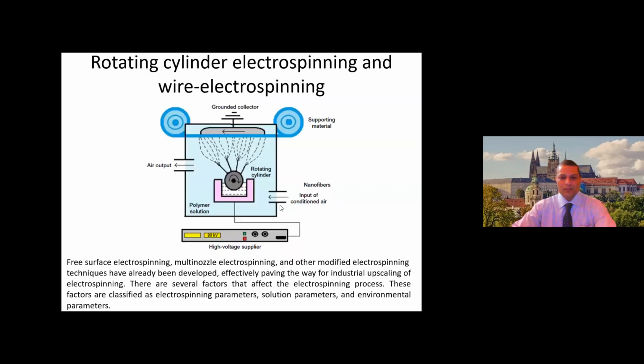between the two electrodes. The previous slide which showed needle electrospinning is only for small scale research in the laboratory. However, if we want to produce large scale nanofibrous material, we need to have a series of needles, or a kind of cylinder in a bath which collects, due to rotation, a thin film of polymer solution. Why do I call it polymer solution?